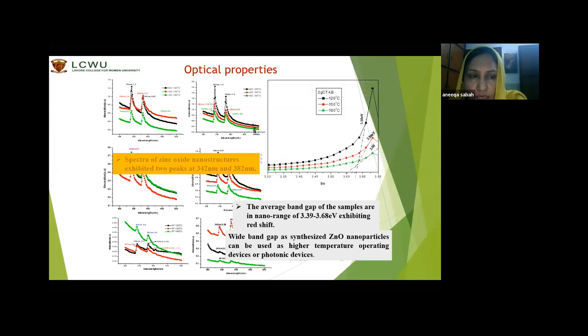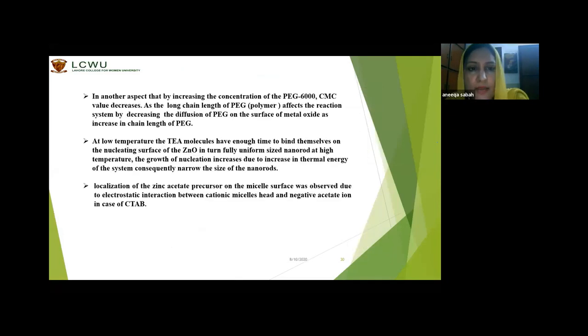Similarly, increasing the concentration of PEG decreases the CMC value, as the long chain length of the polymer affects the reaction system by decreasing the diffusion of PEG on the surface of metal oxide as the chain length of PEG increases.